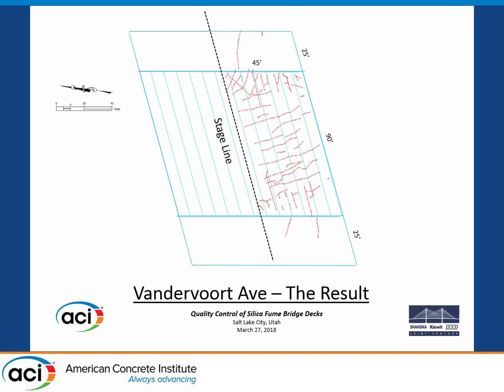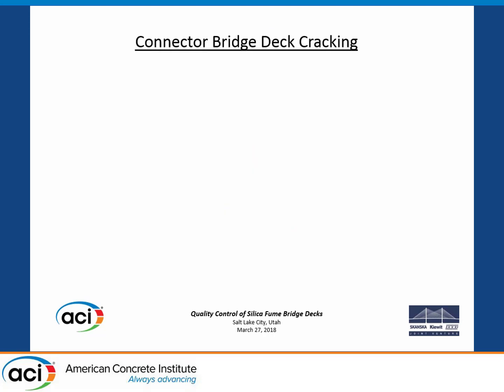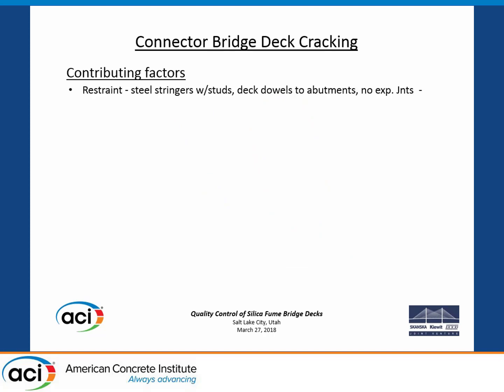And this is what we got for our trouble here. And you can see again the aspect ratio, the crack across the middle, and probably these cracks are here due to all that restraint on the back wall, where the back wall ties into the slab. So a lot of restraint and probably too much heat. Anyway, so connector deck. Contributing factors: restraint, stringers with studs, dowels into the abutments, no expansion joints.